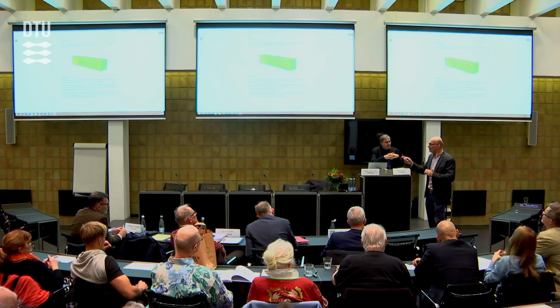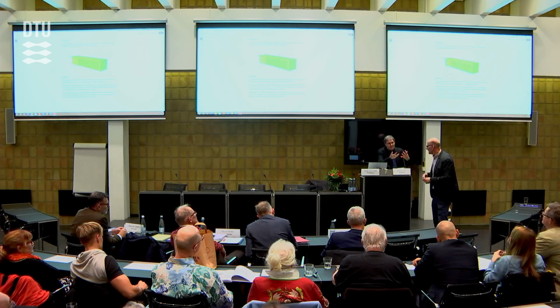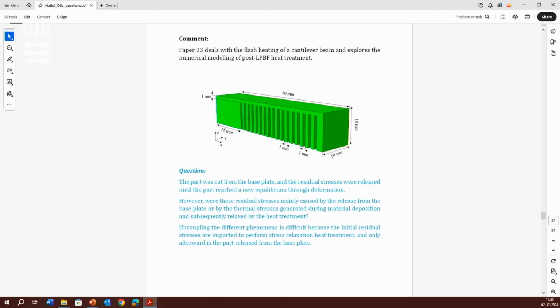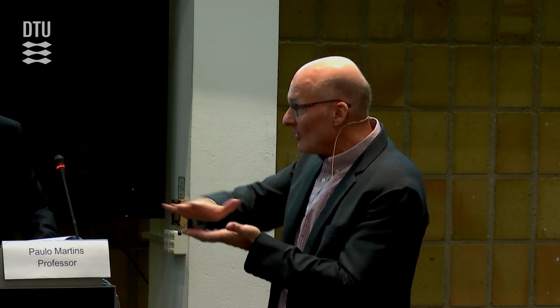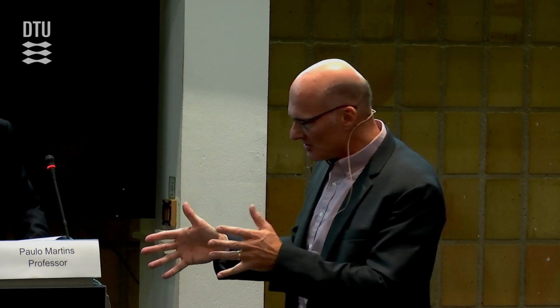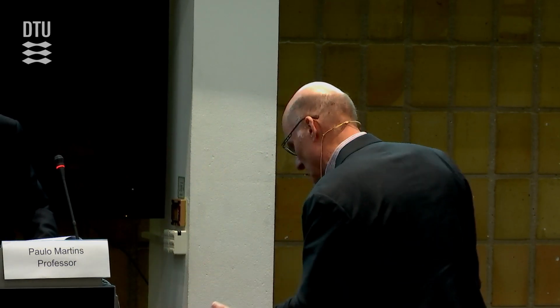Yeah, yeah. So what we did there was that, what is the most relevant? Right? Okay. So what we did was that we simulated the 3D printing process of this, including the supporting structures. That was simulated in layers with a sequential flash heating method, I think. And there, of course, you do get locked-in residual stresses from the process because you have a thermal history, and so the temperatures are varying in time. And then you calculate the transient stresses, and then when it cools down, you get the residual stresses.